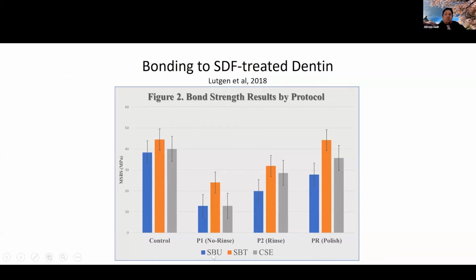So we have Scotchbond Universal and we have Clearfil SE Bond. And we did Scotchbond Universal in the self-etch mode and the total etch mode, so with phosphoric acid etching. And then we have the Clearfil SE Bond, of course, two-step gold standard of 6th generation adhesives that we'll talk a little bit about next week. So we found that both total etching of dentin and use of the two-step self-etch was effective after rinsing of the silver diamine fluoride off. So here is a very important point, because if you look at the American SDF, which is by Elevate Oral Care, in the instructions, it doesn't talk about rinsing, but you have to rinse.